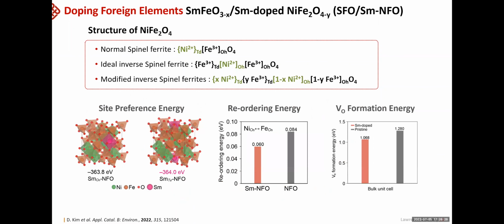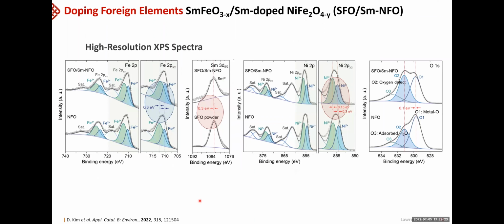So we collaborated with a professor in Korea, and we found out that when you have the samarium dopant, they more preferably go into the tetrahedral sites, which is coincident with the Raman observation. And by doing this doping at the tetrahedral sites, it actually facilitates the transfer of the nickel octahedral site with the iron octahedral site, which means the reordering energy has been reduced. So it can help to push the nickel to occupy the octahedral sites. At the same time, the samarium doping can lower the oxygen vacancy formation energy, so it can produce more oxygen vacant sites. So we did the XPS analysis.